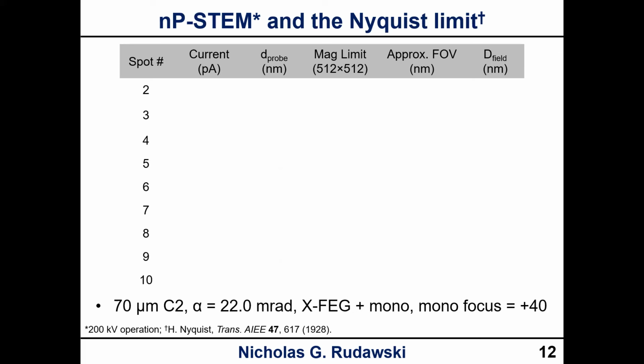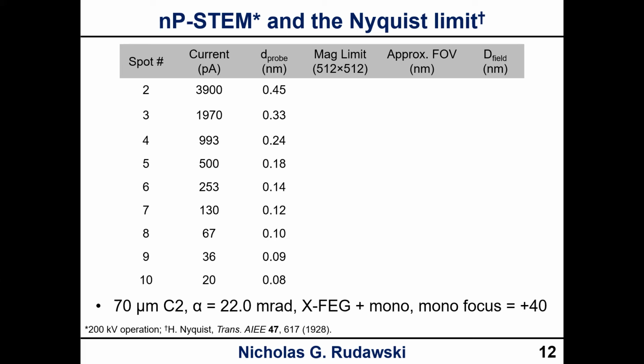We do the same thing with nanoprobe mode, and we see the same behavior with spot size. So as the spot number goes up, the current goes down. We can do the same thing with the probe size. But what's really interesting here is basically all the way up to about 1 nanoamp of current around spot 4, we can still get atomic resolution. Okay, so that's a 2 angstrom probe, and that should be capable of giving you atomic resolution. So you'd have to basically exceed a nanoamp of current before you start to run into a potential problem there.